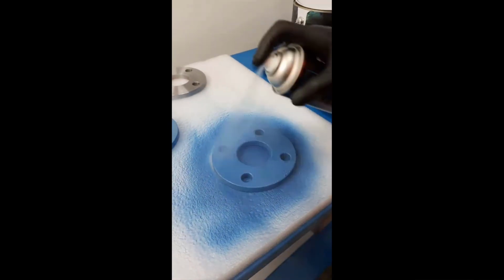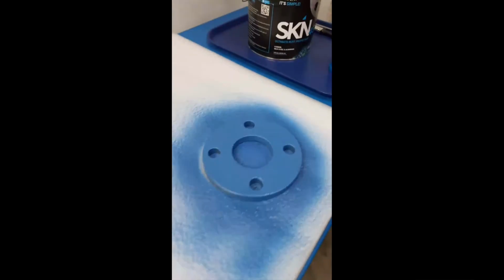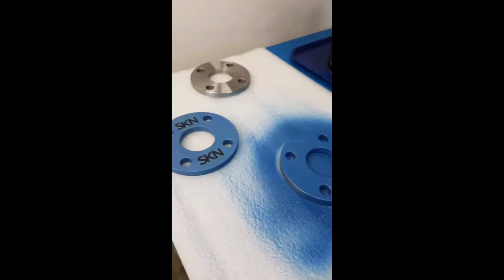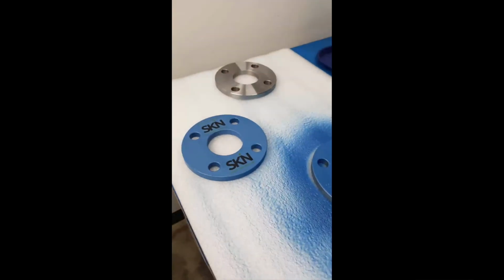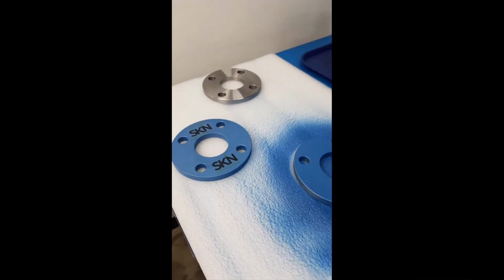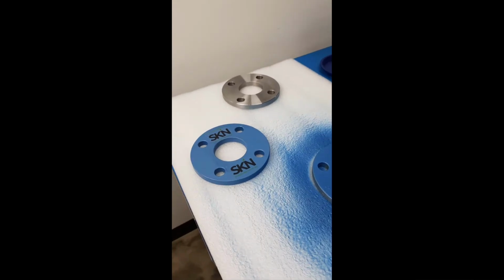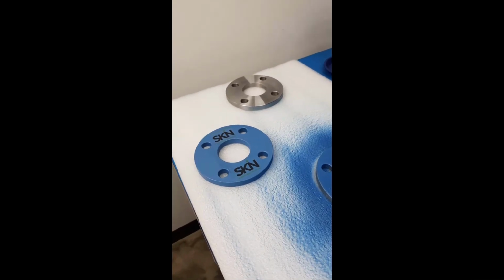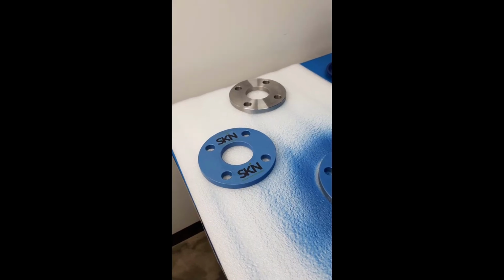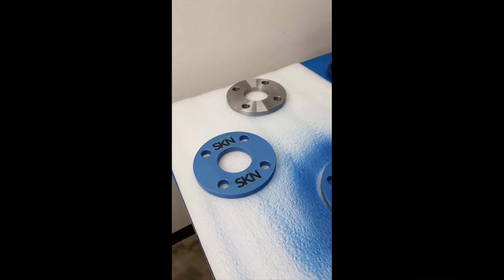What we've also found is that some of the feedback from some of the EPCs that have used it over the years, whether that's in brush form or aerosol, and perhaps particularly in brush form, is that it's been very effective to do the first coat in a circumferential direction, and then the second coat in the direction of the radius, so a radial direction. So you have almost a cross weave of coating that minimizes the likelihood of any pinholes, penetration or leaving out any gaps.